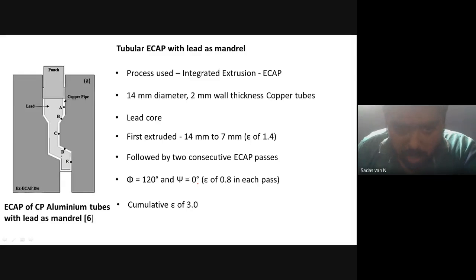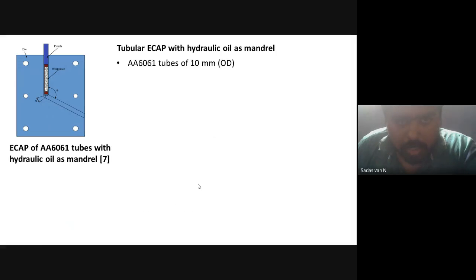So you have to know where to stop. So that is very important. Tubular ECAP with another method, where I fit the ends of the tube with some threaded lids and fill it with SAE 30 hydraulic oil, and then I do the same. It's somewhat similar to the first method, but here instead of sand, I am putting in hydraulic oil.